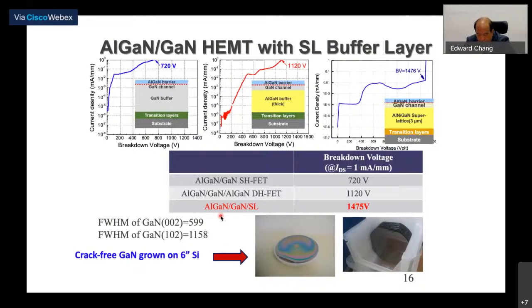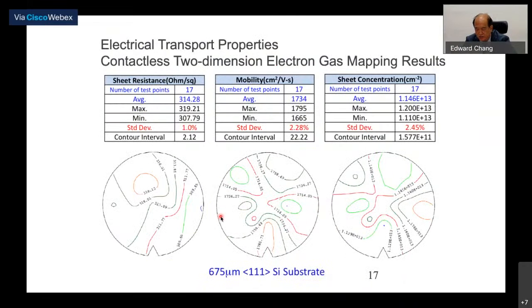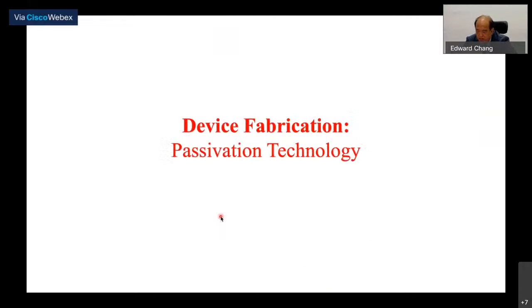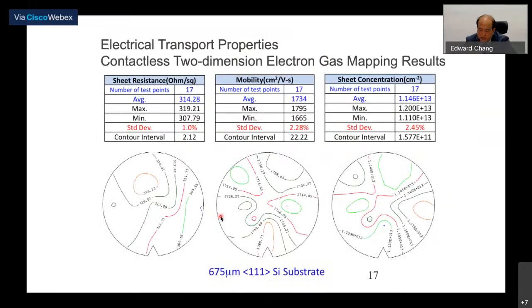And there's a picture showing you the crack-free 6-inch gallium nitride epitaxial layer grown on silicon substrate. And the uniformity is sheet resistance within 1%, mobility 2.2%, and can go up to 1800 centimeters square per volt per second, and sheet carrier concentration is only 2.5%. So actually, this just shows you this kind of technology is quite applicable to industry already.